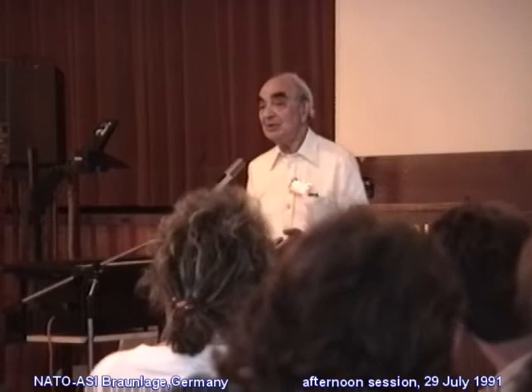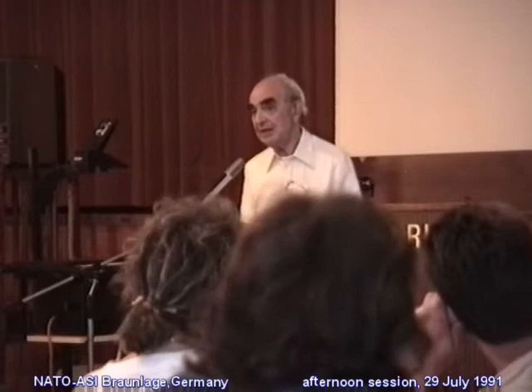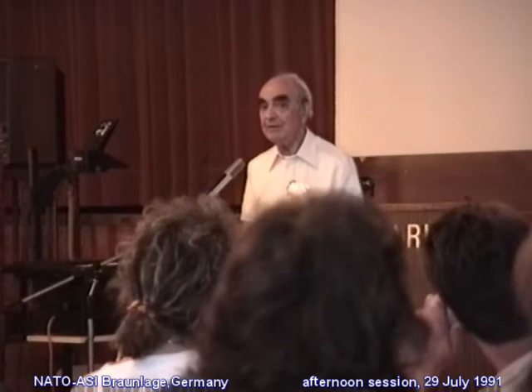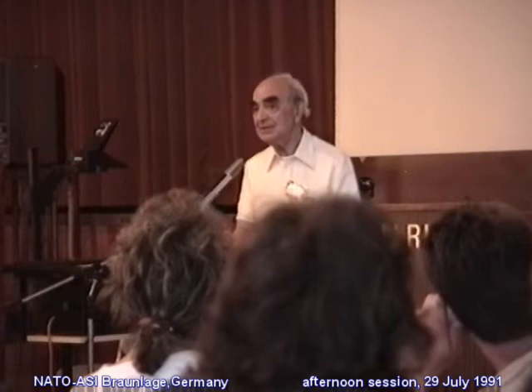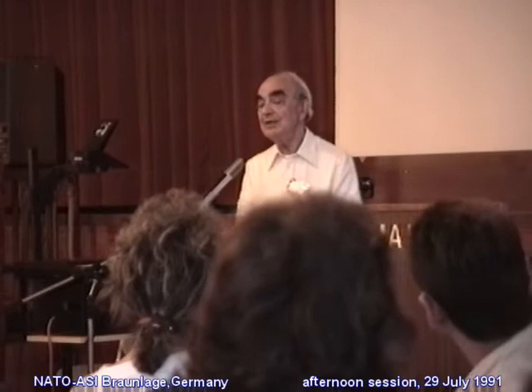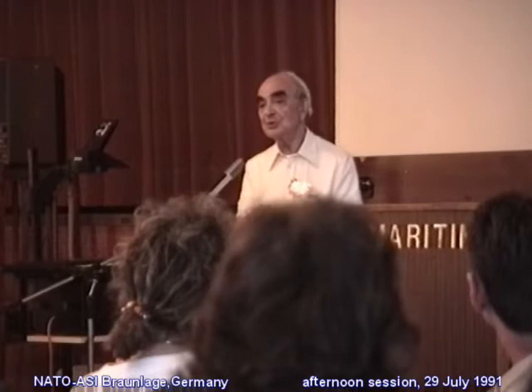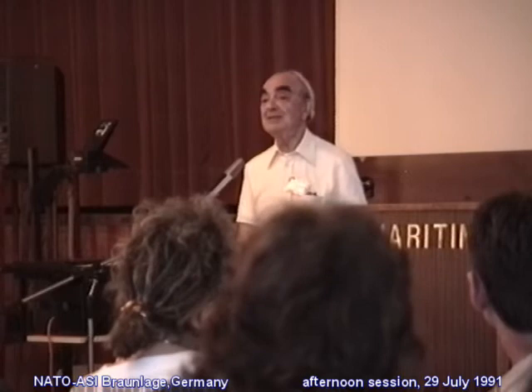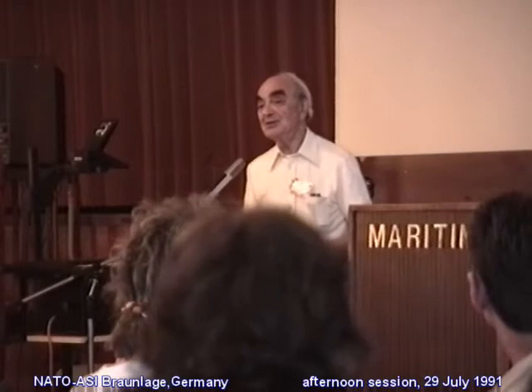And certainly for surfaces which are in contact by Laplace forces where no chemical bonds are involved, I find it hard not to believe in the model that I presented, where as the surfaces begin to separate, the forces between them fall off. And if they fall off slower than the rate at which elastic waves can travel through the thing, I think the elastic distortions will relax and no work will be done. I accept the possibility that in real life and real experiments, you can't do it, something else gets in the way. And I'm not sure whether what you described is a fundamental physical concept or whether it is part of an artifact of the way in which the experiment is done. I'm not being critical, I'm just trying to think about it.